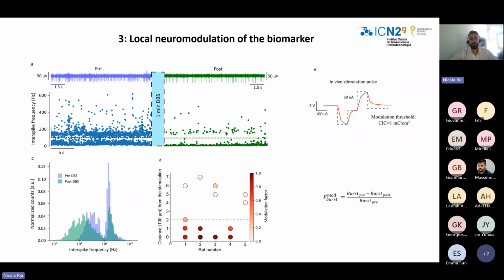After 1 minute of deep brain stimulation, we look again at the brain activity, and what we observe is that the activity is tonic, so there are fewer bursts, and the band associated to the biomarker is attenuated. The same result can be evaluated also by looking at the quantification of the number of counts of the interspike frequency, and the peak of the burst is less than half after stimulation compared to the pre-treatment.